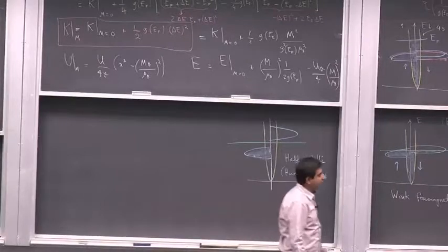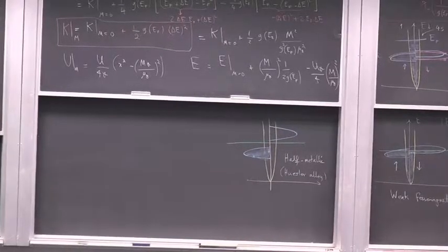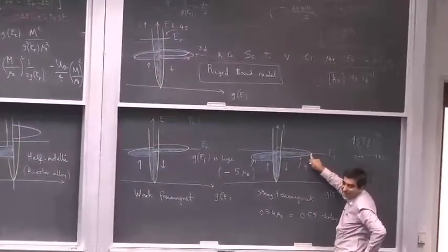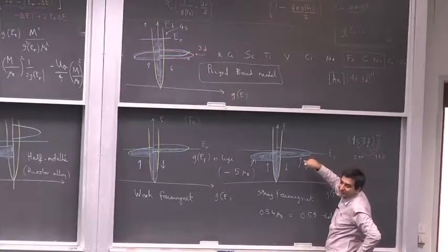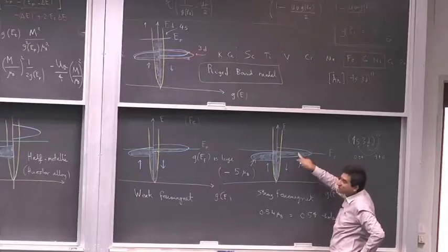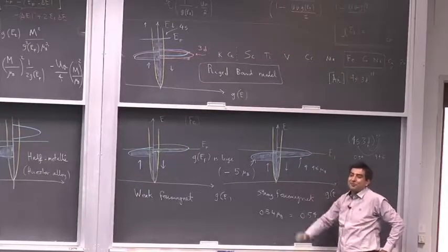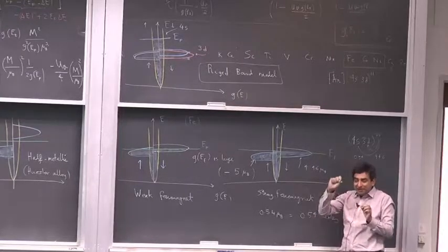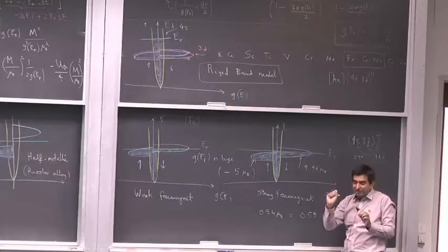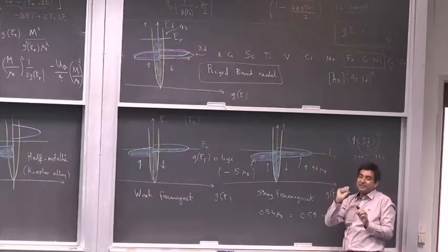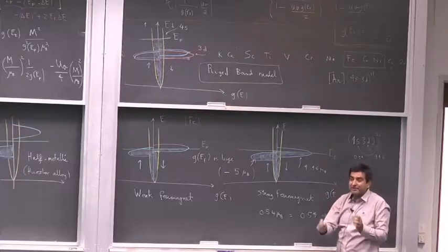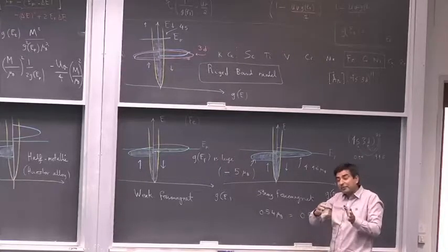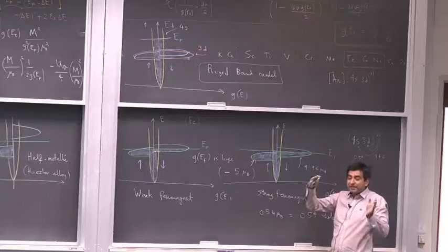If you talk in terms of spin polarization, remember, in this particular case, if the Fermi level intersects with one of the 3d bands, it is actually intersecting with the minority spin band. So if you have conduction in such a material, then that conduction is actually due to the minority spin carriers, or due to the holes. Keep in mind that electrical transport in magnetic materials is of prime importance. That's why you have GMR, colossal magnetoresistance, tunneling magnetoresistance, and anisotropic magnetoresistance.